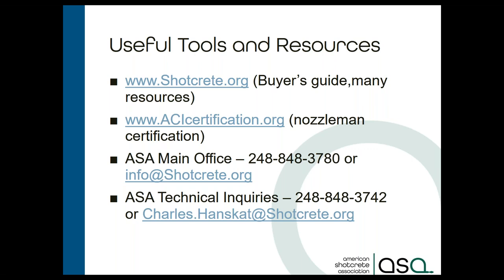We'd like to open up for questions. The first question: what shotcrete mix would you use on frozen ground? You're not going to shoot on frozen ground because it will freeze the paste interface. If it's frozen ground, you're doing cold weather concreting — the materials need to be 50 degrees. What you may do is shoot a stabilizing sacrificial layer, because that interface is going to freeze and you're not going to get strength in that concrete. You can shoot a sacrificial layer that gives you a surface to then build your main thickness with.